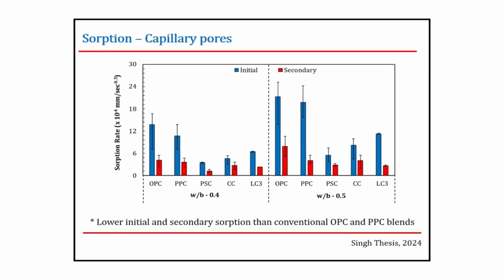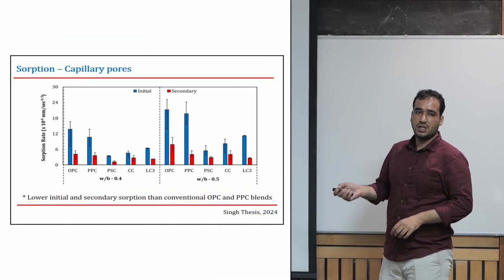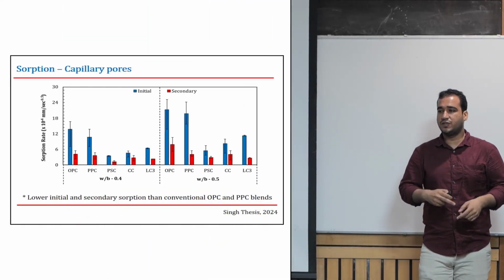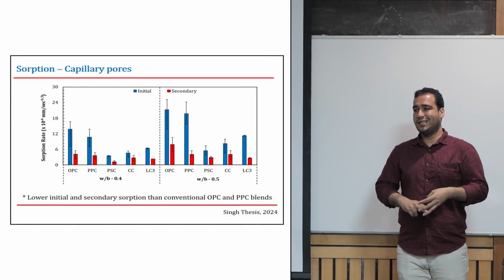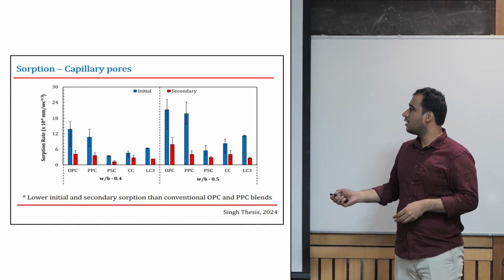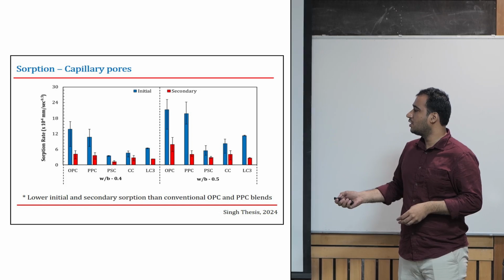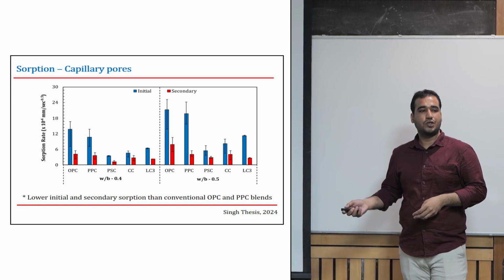water into the concrete. If you see here, compared to the OPC, the blended systems always try to have a lower value, especially the blended systems at 0.5, the ones with the slags, composite cements, and the LC3. They give a much lower initial sorptivity and much lower secondary sorptivity at both the water to cement ratios.